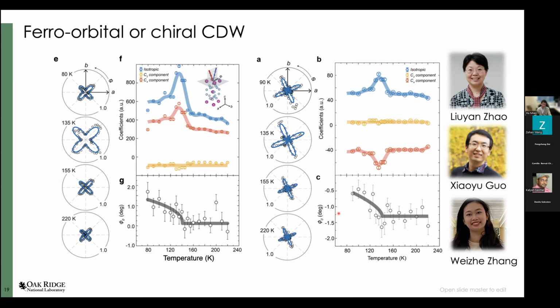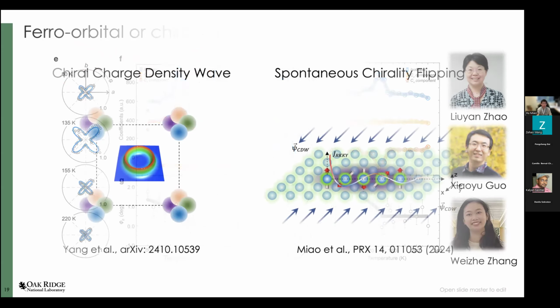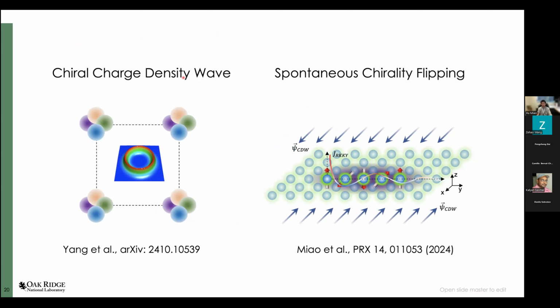So based on all the measurements and based on the subgroup of the high temperature phase, we basically conclude that europium aluminum 4 is either a ferro-orbital charge density wave or a chiral CDW. The difference between these two is that with the chiral CDW, you're going to have a left-handed chiral CDW and a right-handed chiral CDW. So basically, we cannot distinguish the domains or the ferro-orbital CDW. But nevertheless, all these measurements suggest that there is a chiral lattice distortion in the CDW phase in europium aluminum 4. So that's basically the conclusion about our understanding of the CDW phase in europium aluminum 4.